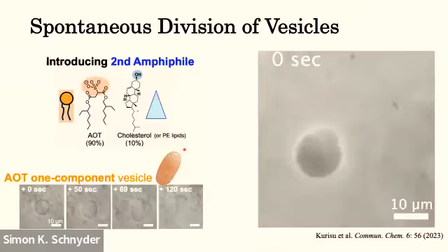Yeah, but here I have to say that 10% cholesterol is the initial condition, but I changed the value of the cholesterol concentration, and when the cholesterol concentration is reduced to only 1%, cholesterol inclusion still successfully results in vesicle division. So I think the dilution of cholesterol is not so big a problem. Yeah, but if you eventually want to divide it correctly forever, okay.